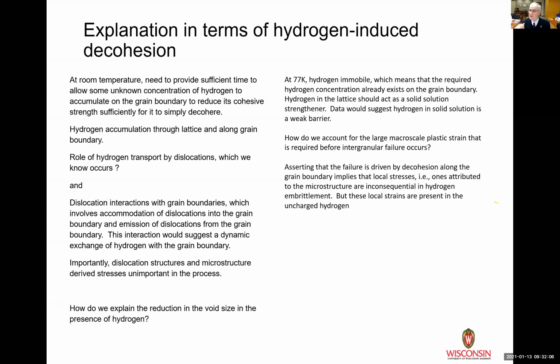It also says that if we're not moving hydrogen by dislocations, and that the diffusion through the lattice or along the grain boundary is low because of the temperature, it says that the starting hydrogen concentration is the one that's important for inducing the decohesion. Right? That to me, that's what that result tells me.